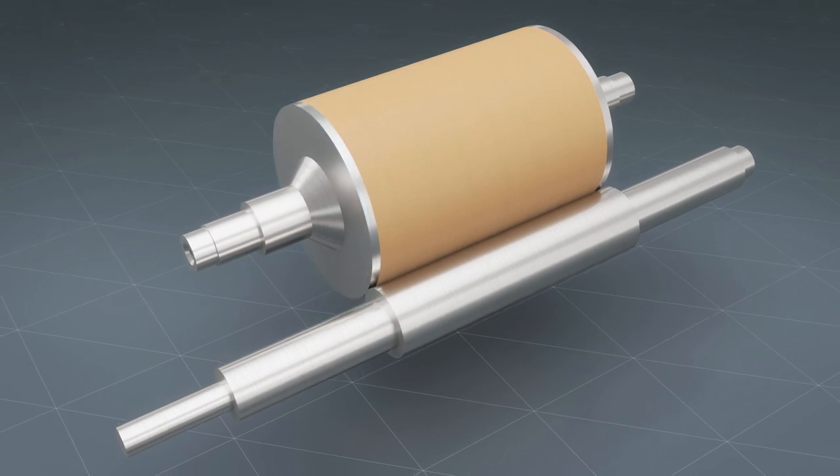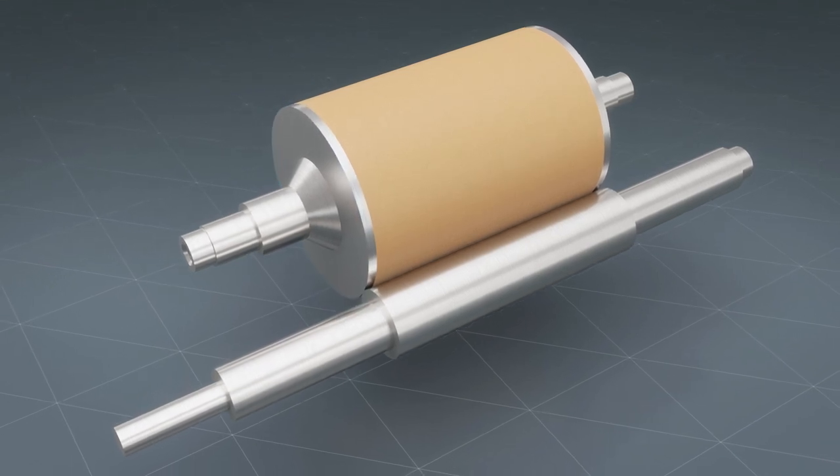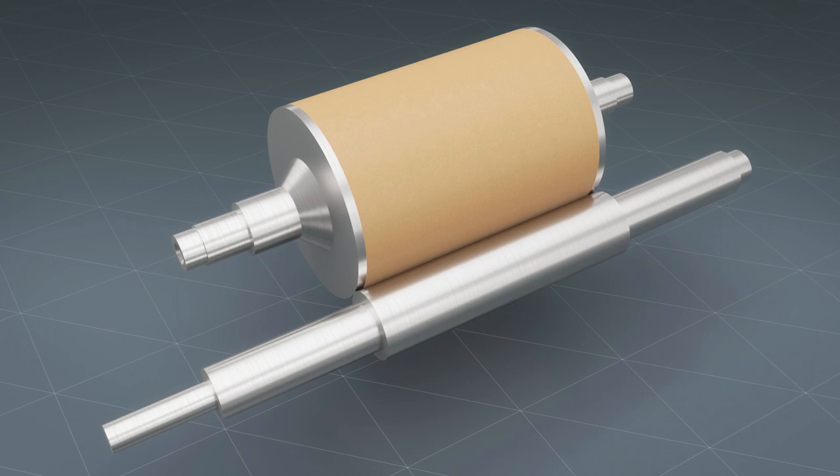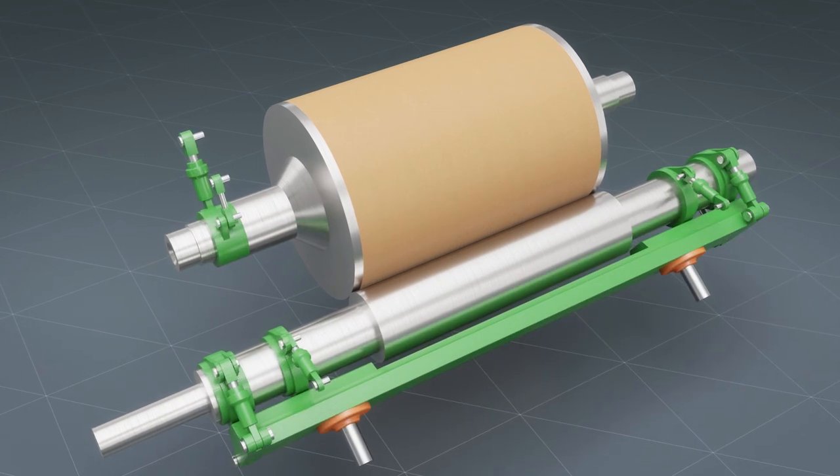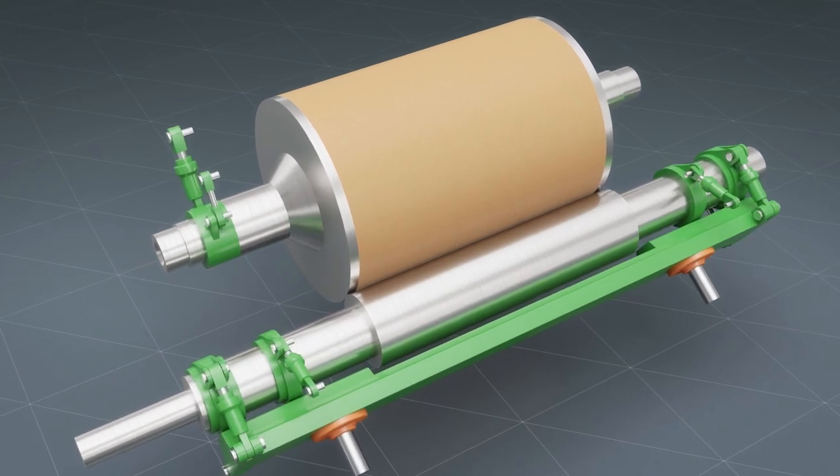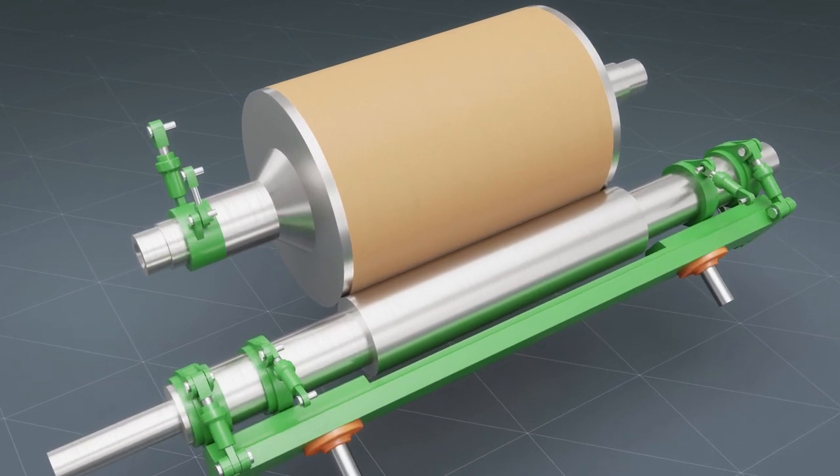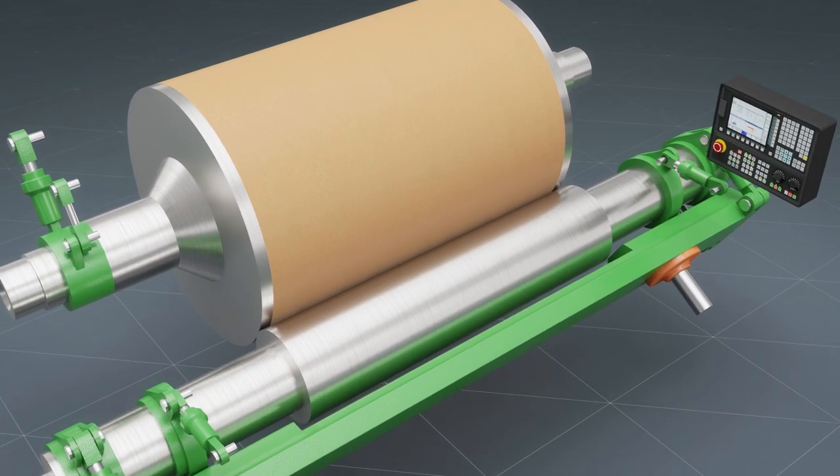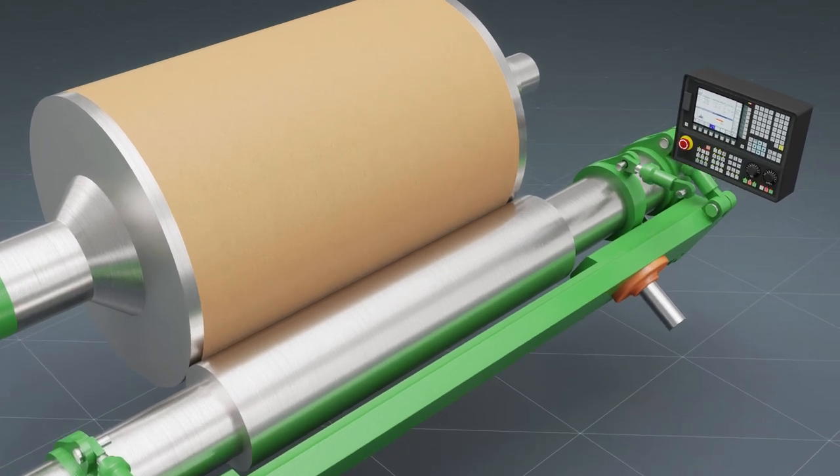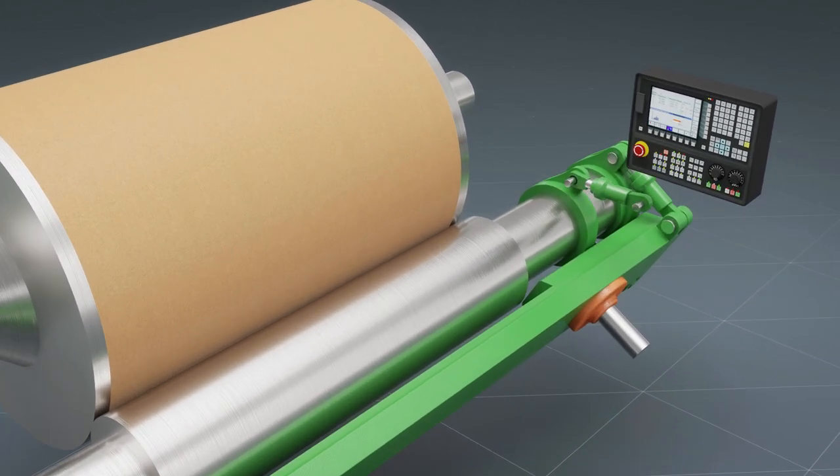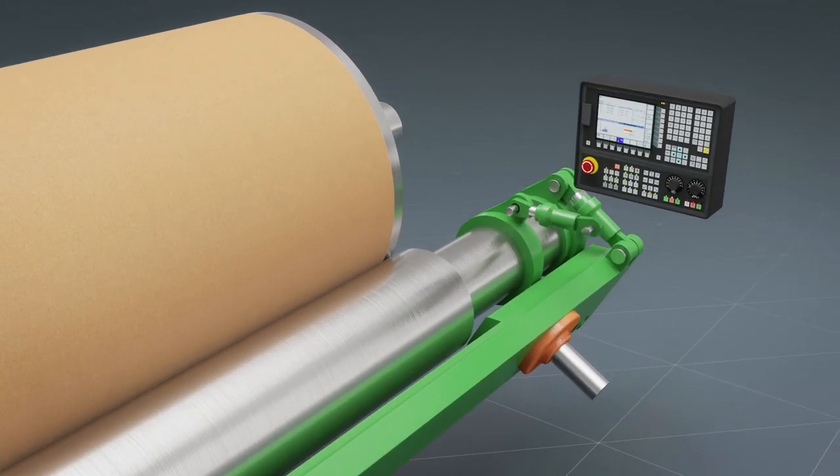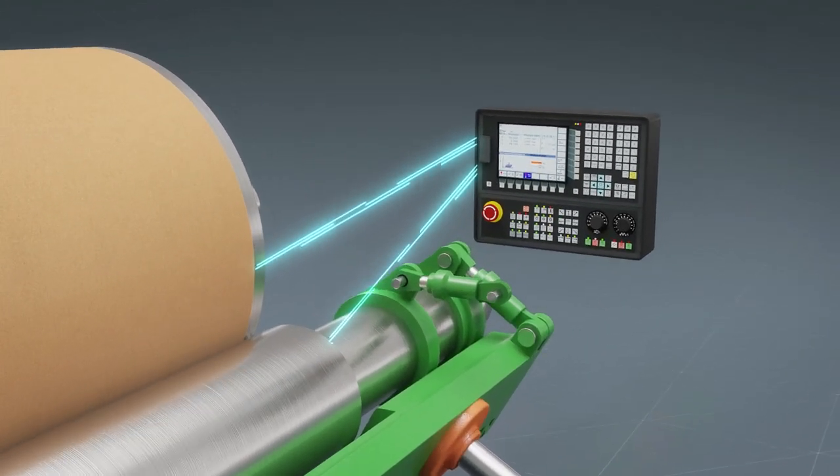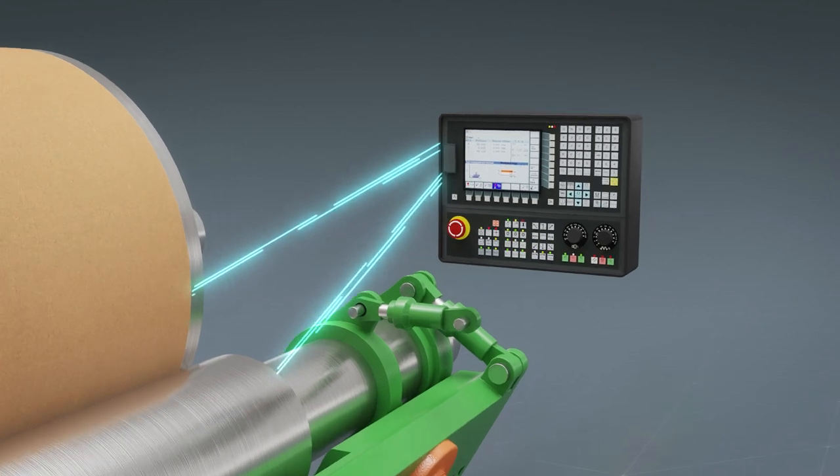As the sheet gets thicker, the rotational speed slows and pressure increases from 5 tons to up to 30 tons. The process control system automatically adjusts speed, roller pressure, and temperature as sheet thickness increases.